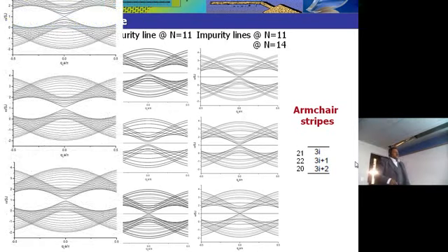The first one here is 20, belonging to 3i plus 2. We don't have a gap here, but we have a point contact at the Dirac point here. But for the case 3i plus 1, we have a gap here. This result coincides exactly with electronic graphene stripes, which shows that we have coincidence between electronic graphene and the magnetic stripe with nanodots when we solve the dispersion relation.